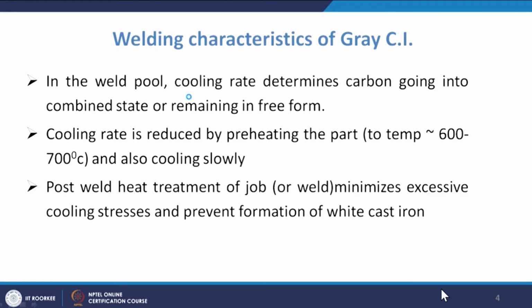Okay. So for the welding characteristics of gray cast iron, in the weld pool the cooling rate determines whether the carbon goes into the combined state or remains in the free form. So the cooling rate is reduced by preheating the part to a temperature of 600 to 700 degrees centigrade, and also cooling slowly.